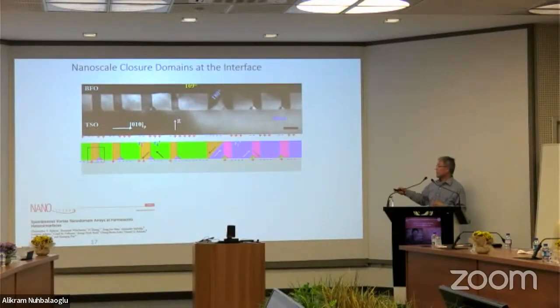This is just a cross-section TEM image of a ferroelectric. This was polarized, grown on a substrate, which is an insulator but has a similar crystalline structure as the ferroelectric. So this interface is coherent. The ferroelectric is insulating, with a multiple domain structure. The boundary between the domains, this straight boundary, is a domain wall. The polarization will change from here to here to here. It just changes by a 180-degree rotation.